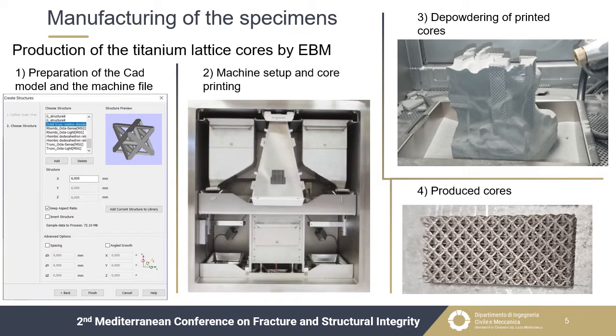As concerns the manufacturing process of the cores, after having defined all the geometric parameters, the first step consisted in the creation of a virtual geometrical model. For this purpose, the Materialise Magics software was adopted that was able to draw a lattice structure in a specific volume. Therefore, only the dimensions of the parallelepiped representing the core and the type and strut diameter of the cell were necessary. Once the CAD model was ready, it was exported in the slicing software of the 3D printer. The machine used was the Arcam A2X, while the relevant slicing software was the Build Assembler.